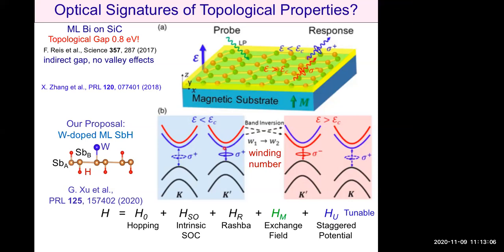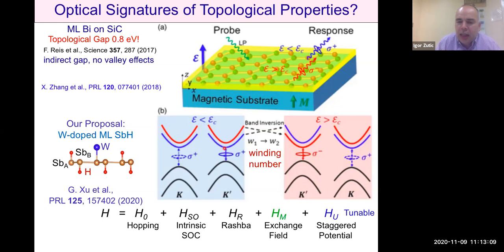Thanks very much. And what we were excited about is that unlike in many other cases where these changes would imply comparing sample A and sample B, we can do it in a single sample, at least theoretically, based on tight binding, Bethe-Salpeter, and first principles calculation. So this is maybe an early example, but I think more of them will follow, because the topological properties could be imprinted in these selection rules, and the structure and behavior of the exciton may reveal this topology.